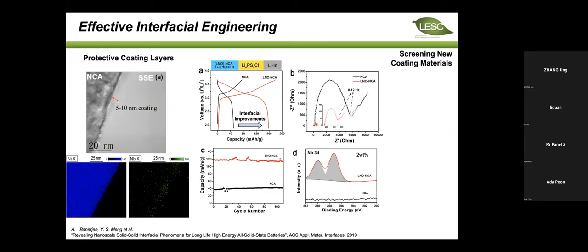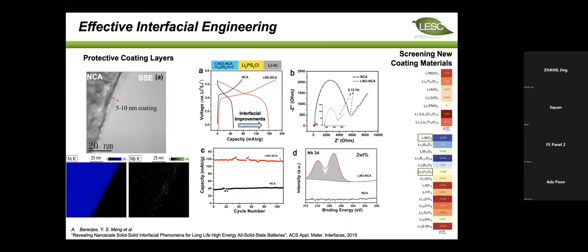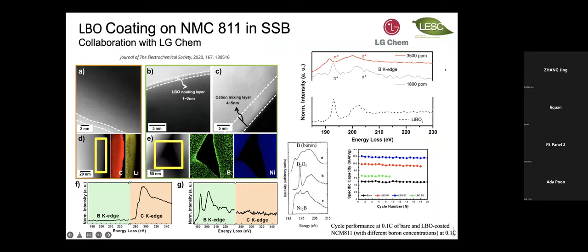I just want to showcase maybe one quick example on the cathode side. The coating is very important for chemical stability, right? Because the oxide and sulfide are not intrinsically compatible. So you need to develop coating materials to stabilize the cathode chemically, and then think about the electrochemical stabilities. And in the case of coating materials for cathode, our field is extremely successful. Not only did we find niobate is reproducible, we found all the phosphate, borates are actually really good coating materials, and they can stabilize the cathode.